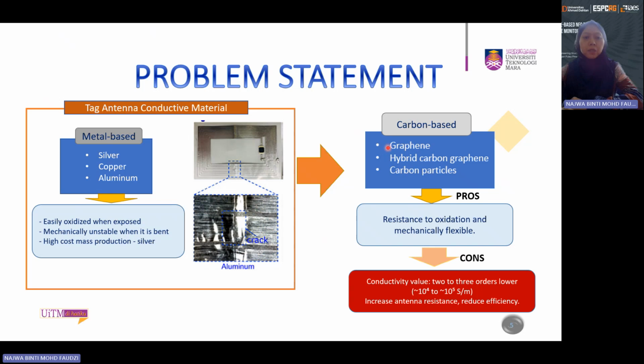But the conductivity of these carbon-based conductive materials, specifically graphene, is mostly 2 to 3 orders lower than that of the metal-based conductive materials. So it is normally in the range of 10 to the power of 4 to 10 to the power of 5 Siemens per meter, as compared to the metal-based, which is normally in the order of 10 to the power of 7 Siemens per meter. So lower conductivity as compared to the metal-based material will increase the antenna resistance and reduce the efficiency of the antenna.